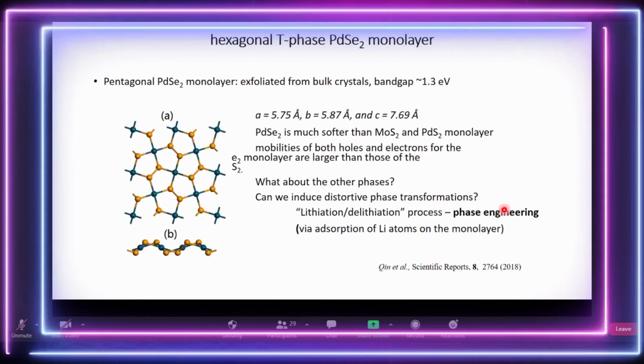So this is the work we're looking at. Earlier we looked into monolayers, different kinds of monolayers, and then we looked into high pressure phase transition. But here the key word is phase engineering. So we looked around and we found there is a PdSe2 monolayer. That's in a pentagonal form. You can see here it forms pentagons. And this is puckered. So this PdSe2 in pentagonal structure is a layered material. So simply like the Scotch tape method, you can exfoliate it from bulk crystals. And it has a nice gap, about 1.3 eV, which is the maximum for solar absorption.